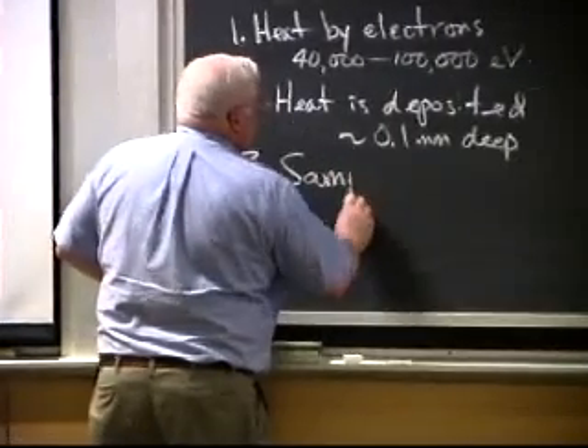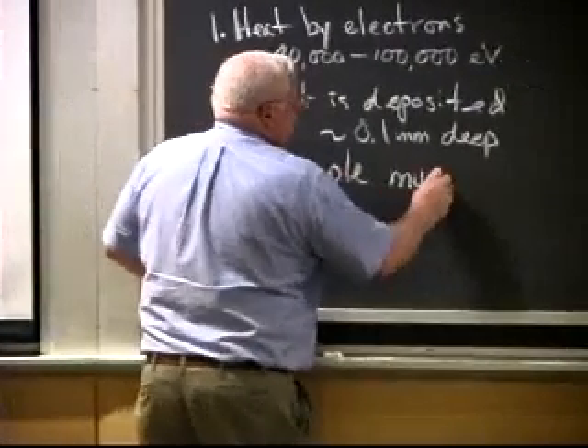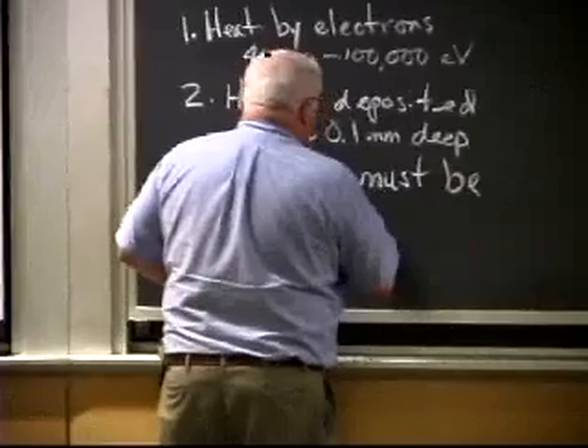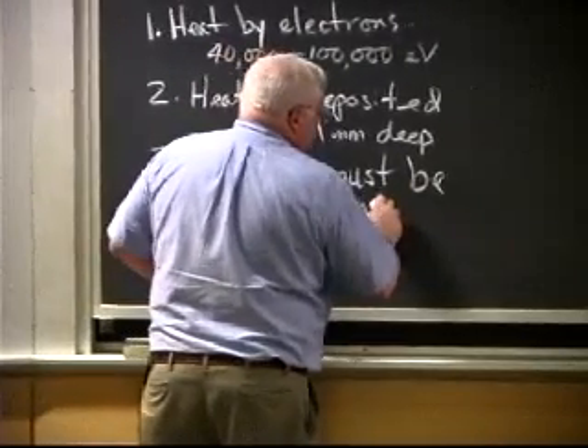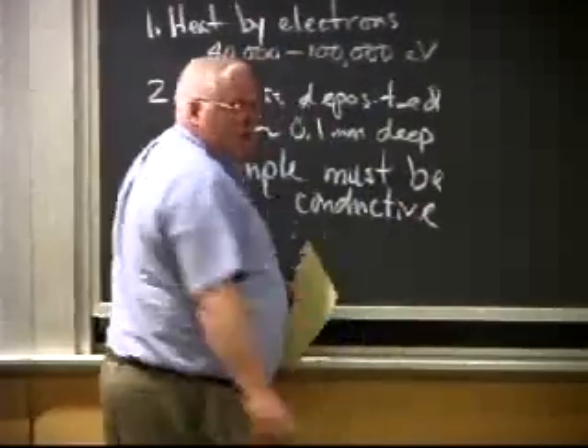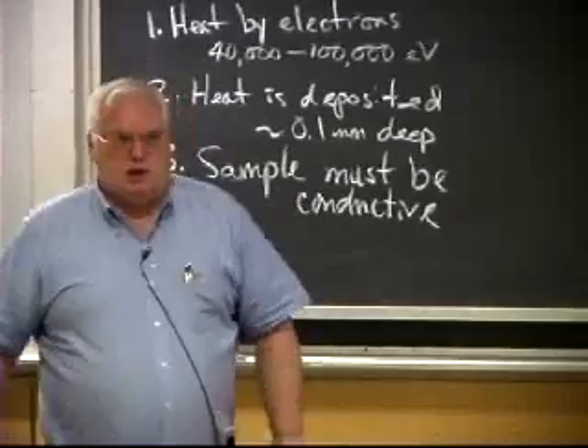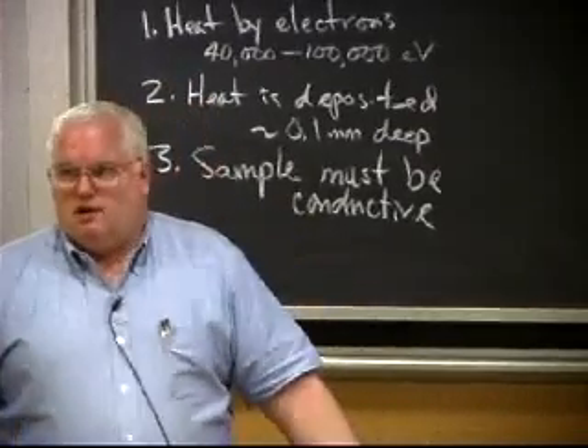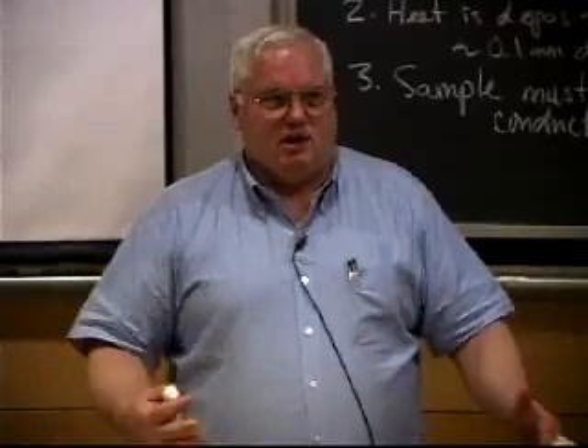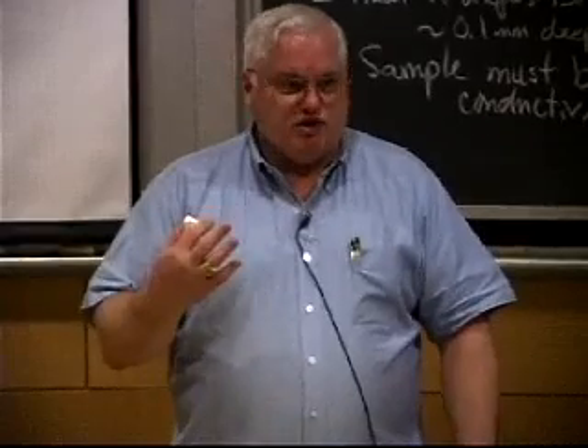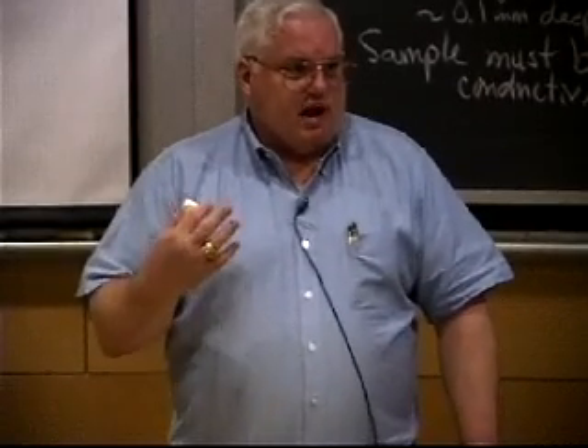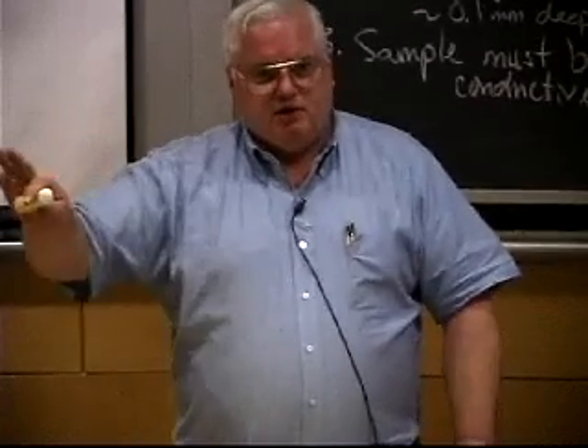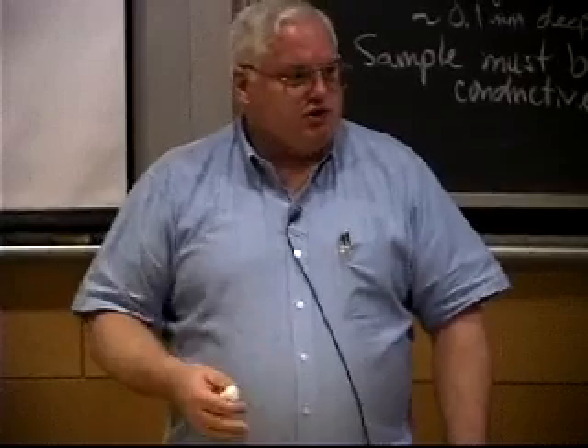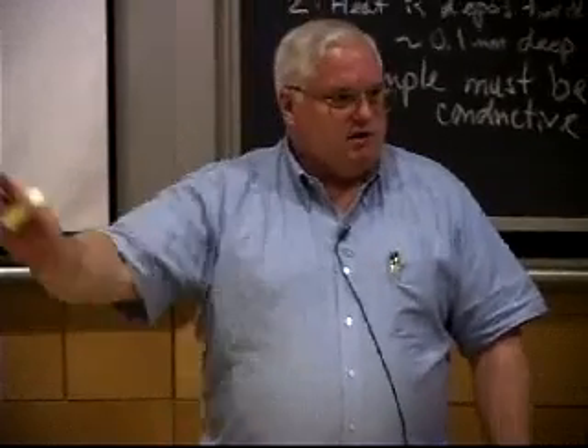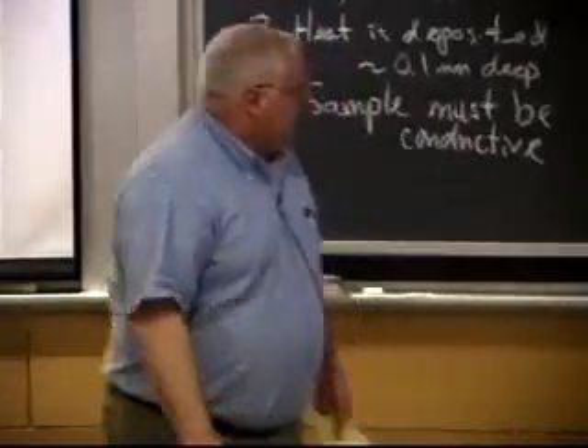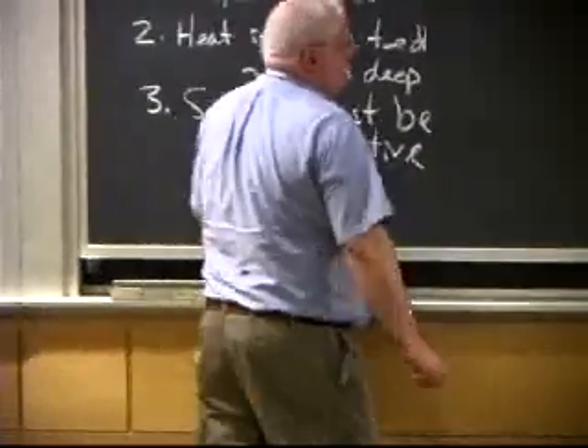In electron beam, the sample must be conductive. And why do you have to have a conductive sample in electron beam? What happens if you were to hit an electron beam against an insulator? It collects electron charge, right? If it collects electron charge, it doesn't take very much charge to build up, to act as a capacitor, and essentially you now start deflecting the beam. Okay, you now have a negatively charged surface. The electrons don't want to go there, so you lose your focus on your beam. So it must be conductive.